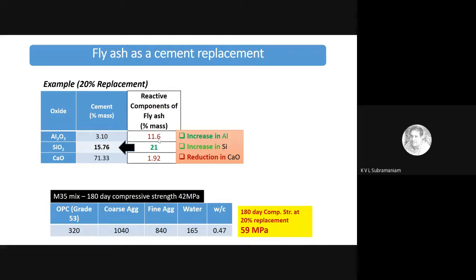And when you actually look at an M35 mix, which was designed for a 42 megapascal compressive strength, at 20% replacement, we were able to achieve about 59 megapascal strength, because net we were able to produce more calcium silicate hydrate in the system.